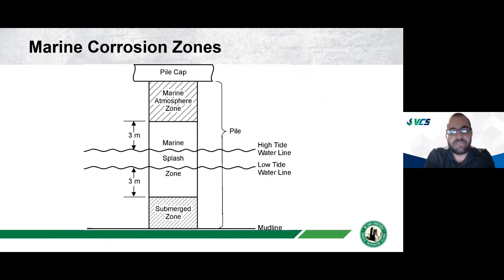This is going to be the most severe environment for corrosion in a marine environment because, one, you have a lot of oxygen available. You have a lot of water with chlorides or sulfates in it. And you have this wet drying effect which will help drive chlorides into concrete and also leave salts on steel structures and things like that. So the marine splash zone is your most dangerous, most aggressive zone, but you have two other zones which are still corrosive, just not as accelerated as the marine splash.